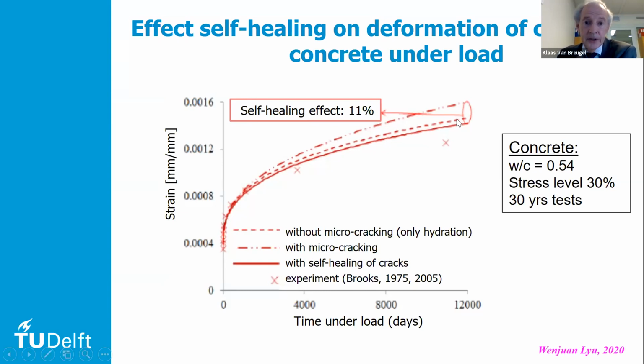And if you then take self-healing of the cracks into account, then you see a reduction of the creep compared to the creep calculation where you have no microcracking. So you see that there is a trend simulated that is also expected from the conceptual performance of a cracked material, that the cement paste around the crack would experience some additional hydration, giving an overall increase of the strength of the material.